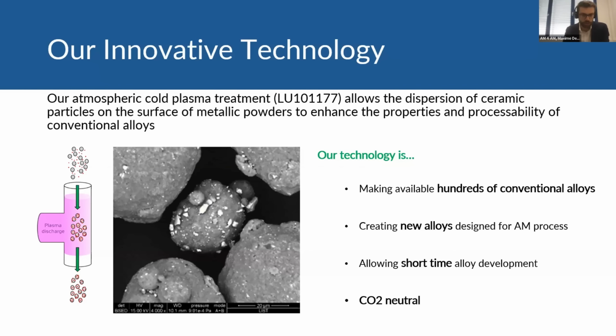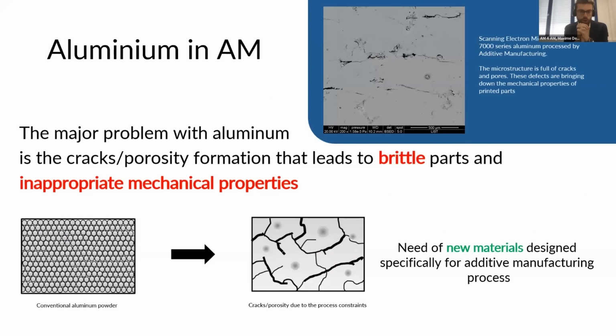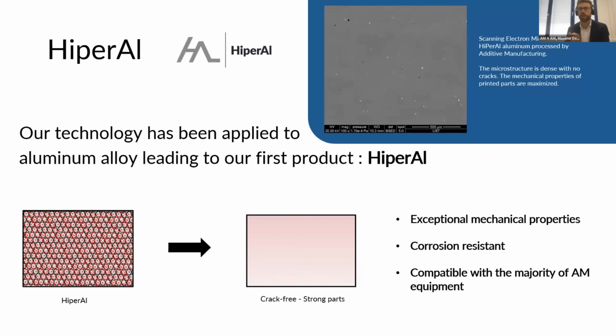So our technology has been applied to aluminium and especially to the 7000 series. To make another short reminder, the biggest problem with such aluminium is that when you process it with additive manufacturing, you will get brittle parts with inappropriate mechanical properties, a lot of porosity, a lot of cracks. You can see on the top of my screen a microscope image full of defects. So it's not possible to use this kind of material to make strong parts. And so there is a huge need of new materials designed specifically for additive manufacturing. And our technology has been applied to these 7000 series to give birth to HiperAl, for high performance aluminium.